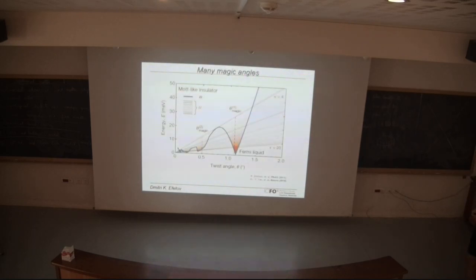Okay, so in principle, there exists not just one magic angle. Again, from Bistritzer and MacDonald, they have calculated, as a function of energy and twist angle, W. W is basically the bandwidth of the underlying Moiré band. Wherever W becomes very small, in these points here, this is where this magic angle condition happens and where the bands become ultra flat. As you can see, the first magic angle arrives at around 1.1 degrees. This is exactly where all these discoveries were made.